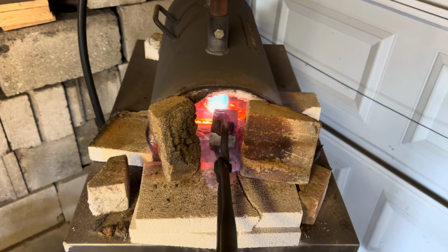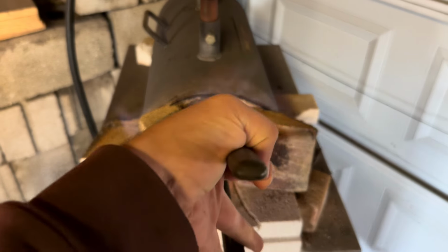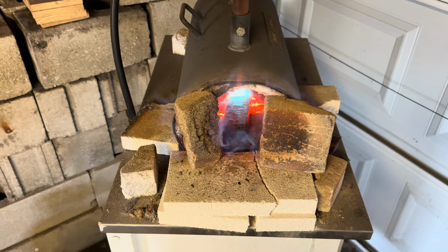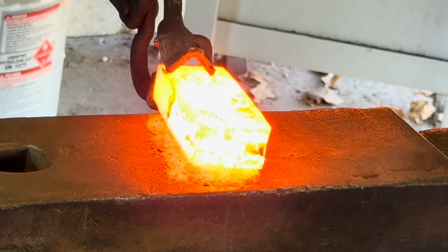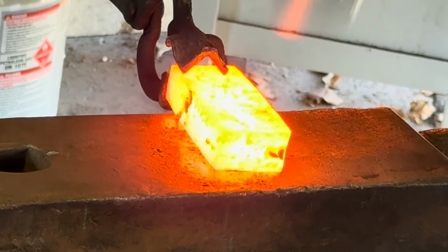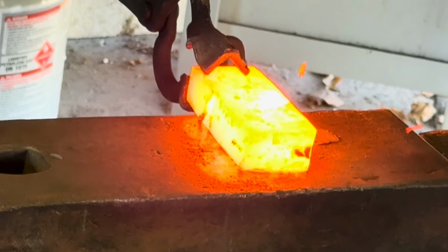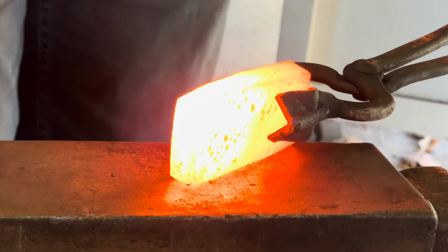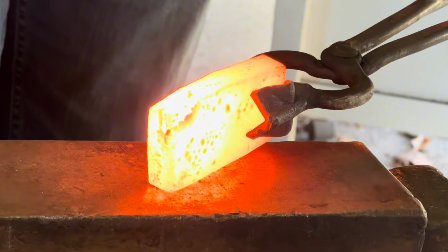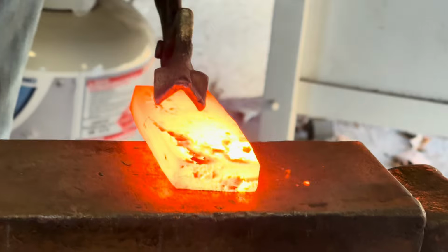Unfortunately, I was right, and the delamination went all the way through the steel, which basically means that almost half of the billet is unusable material. I could not make a knife out of it since it's not welded. But luckily, a good majority of the billet is usable, so I still have a lot of material to work with.